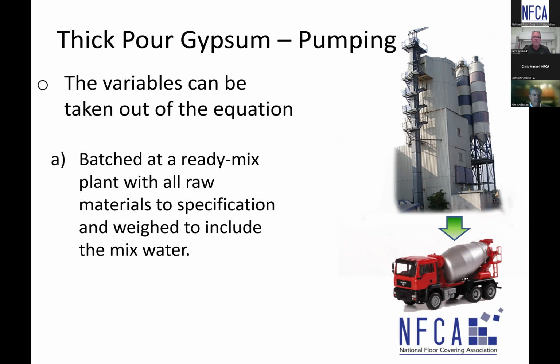Here's another alternative where we take those variables that I talked about out of the equation. This is basically a ready mix batch plant for gypsum. You don't see this very often. I have seen this in Germany where they have a batch plant where the gypsum is weighed properly. The sand is the right gradation of sand. It's weighed properly. The water's weighed and put into a truck and mixed so that everything is precise. But the job's got to be close to the plant, because you don't have all day to work with the gypsum material.